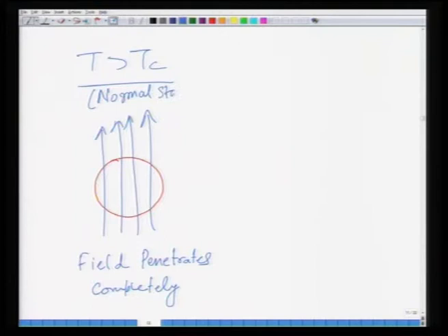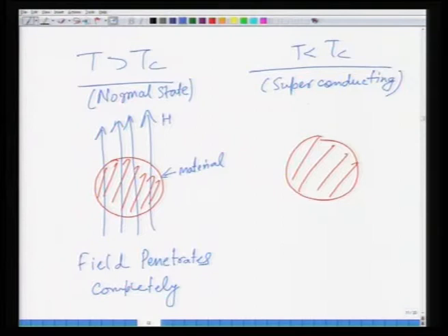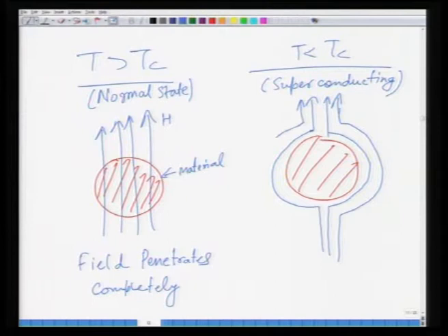And so, this is your material, and this is your field H. Now, when T is less than TC, which means you are in the superconducting state, then when you have this material and when you apply a field, this field is like this, it bends around the sample like this. So, you have massive flux lines on the surface, but nothing penetrating inside. So, the whole of the field that you apply gets repelled, and this